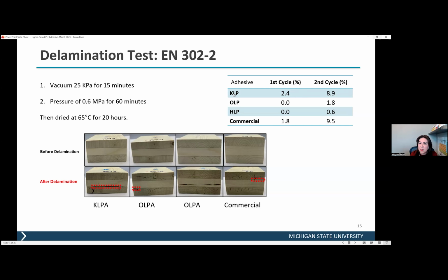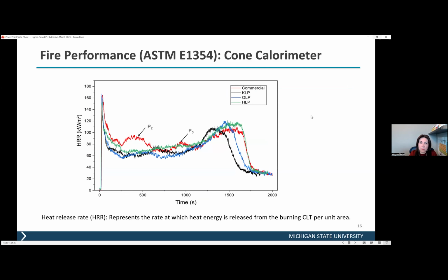After the first cycle, this is kraft softwood adhesives, organosolv hydrolysis lignin-based CLT samples made with the lignin-based adhesives. And then this is the second cycle. Anything below 10% is acceptable by standards. The kraft softwood delamination was higher, but still lower than the commercial adhesives. And then the two organosolv hydrolysis softwood have very, very low delaminations that we see in these samples. All of them are acceptable, but this is another, again, really rigorous test that needs to be done and shows how strong these adhesives are.